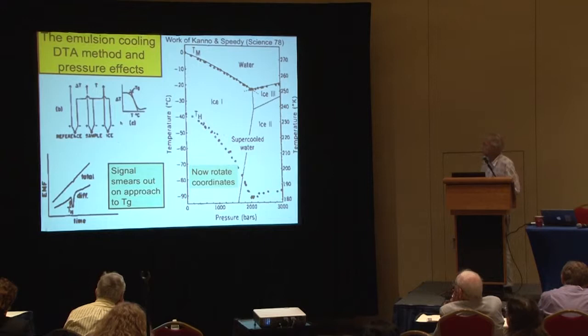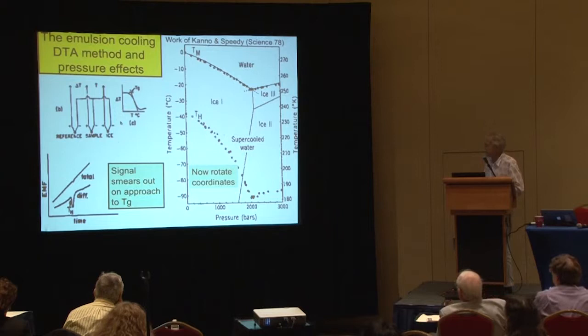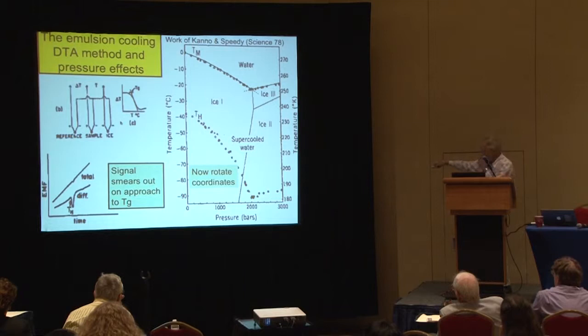Also for pressure, emulsion cooling is very good for pressure effects. And this is a paper we put into Science quite a long time ago with pressure on this axis. Sometimes you see pressure here, sometimes you see pressure in this way. So this one was a pressure increasing over here. And now we see the melting point going down, as everyone knows, to about minus 20. But the nucleation temperature, homogeneous nucleation temperature, going right down to minus 90. And water down here is about as viscous as honey. Yeah, it's a very different sort of a liquid.